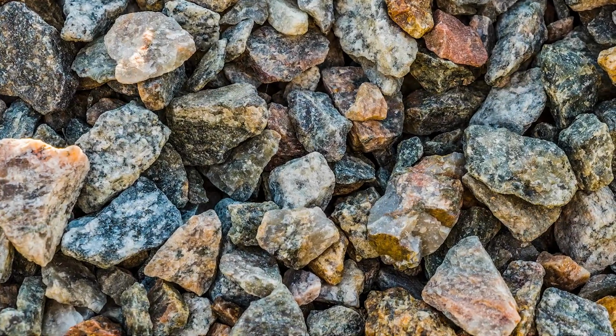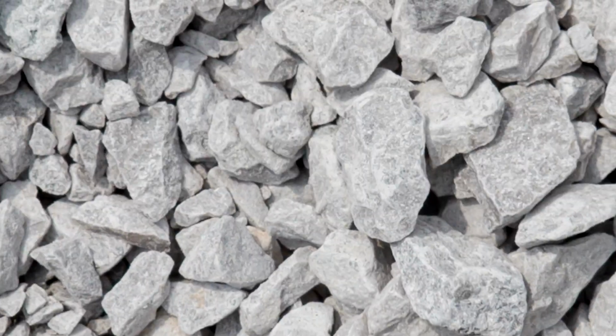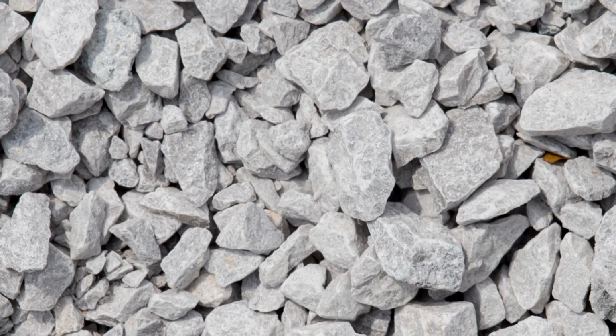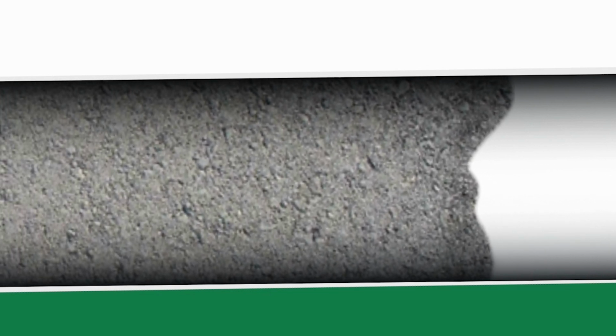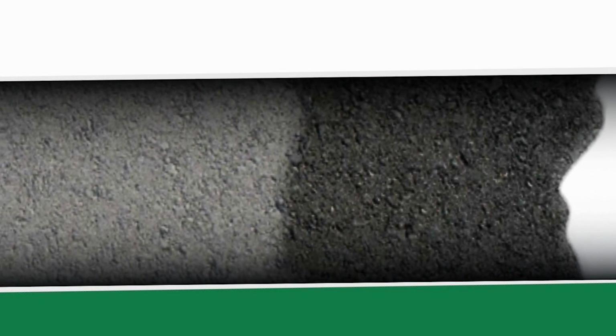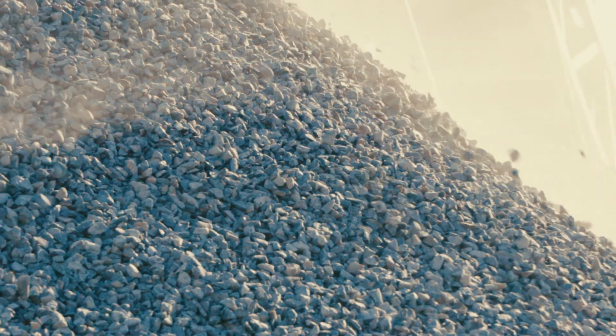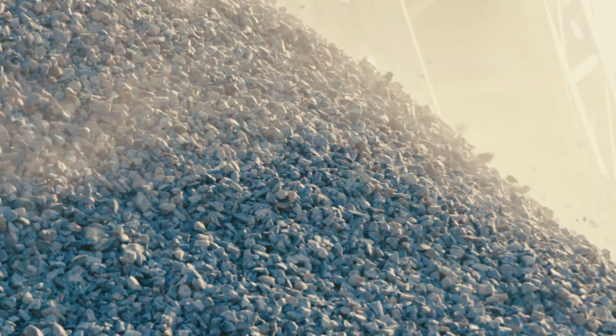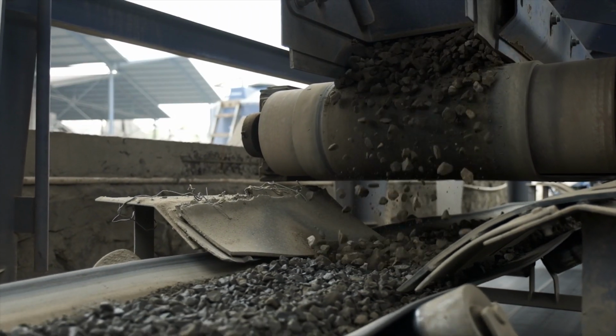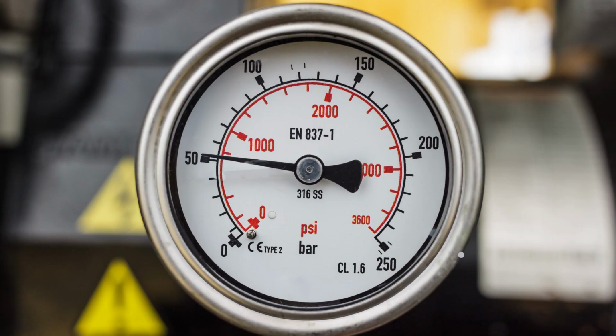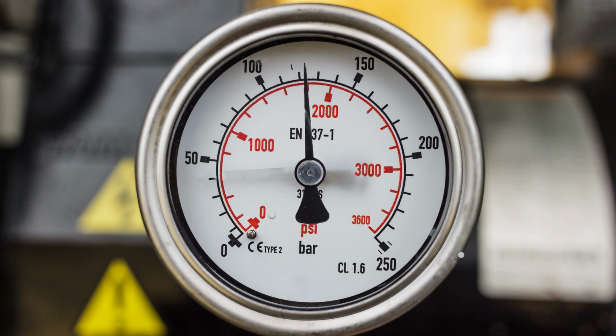Larger, jagged aggregates like crushed gravel or chipped stone can increase friction in the line. This friction not only raises the temperature of the mix, but also speeds up the rate of hydration and can lead to moisture loss. With sharp or irregularly shaped aggregates, there's a greater chance they'll bump into each other or even get stuck, increasing pressure and the risk of a line plug.